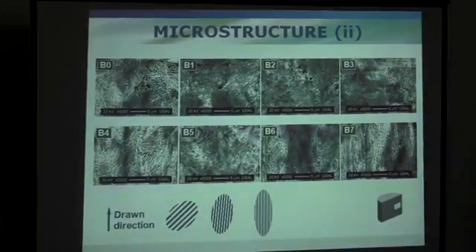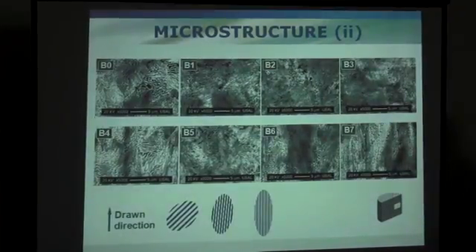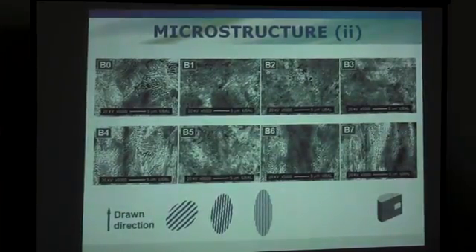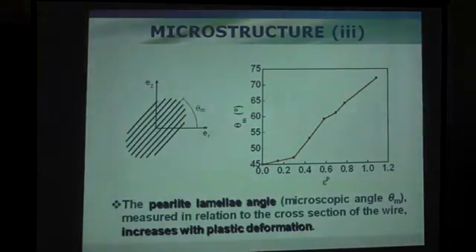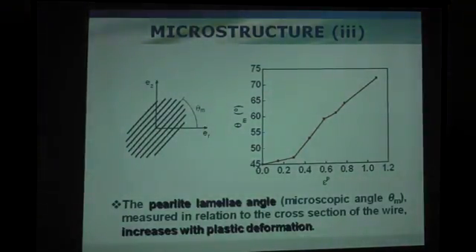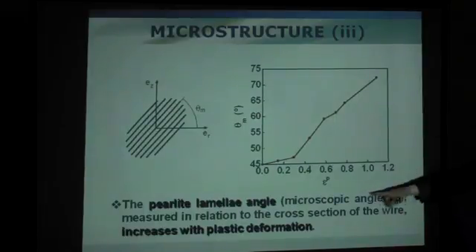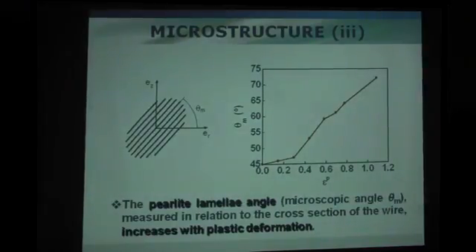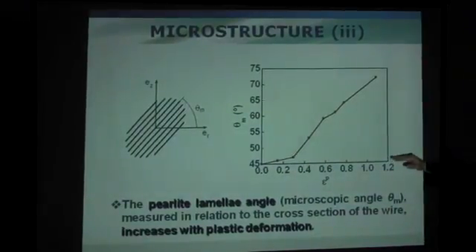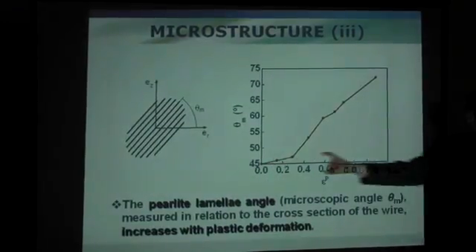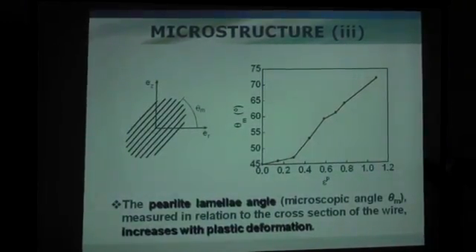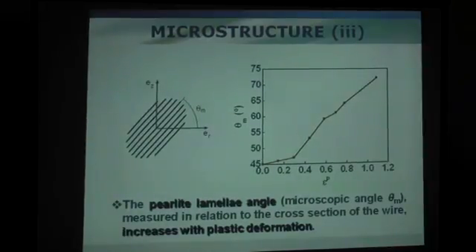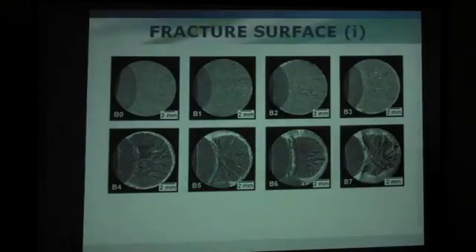But in this case, we have the clear orientation. It is a heavily, markedly oriented material in the drawing direction, the y-axis, with consequences in fracture. Here we have evaluated the pearlite lamella angle, the microscopic angle theta m, measured in relation to the cross-section of the wire. It increases with plastic strain, and it increases with cold drawing. With this imposed plastic strain in heavily drawn steel, the angle of orientation increases in relation to the transverse direction.